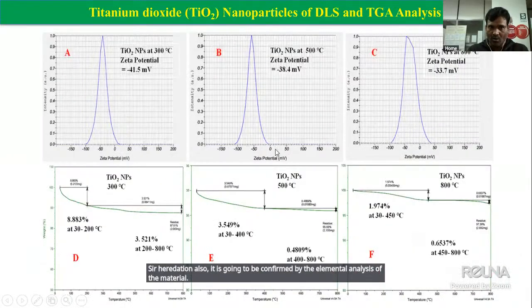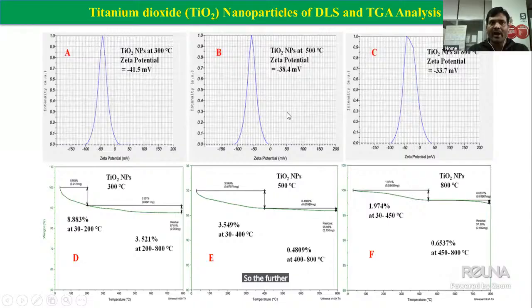Here it shows the circular ring with bright spots, which means a more crystalline nature of the material at higher temperature. Here the EDAX analysis confirms the elemental analysis of the material. So further, we identify the titanium dioxide nanomaterial's colloidal stability and thermal analysis.